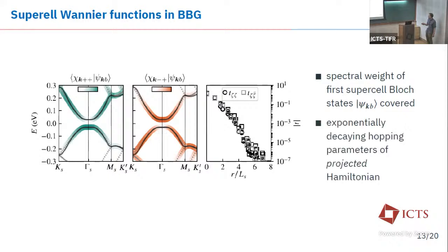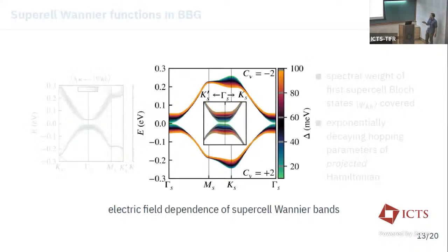As a control, we have plotted the hopping parameters when projecting the Hamiltonian onto those Wannier states, and we see that they decay strongly exponentially, meaning that we have a well-localized Wannier basis for our problem for the Bernal bilayer graphene in the supercell. And what we can do now is we can take those Wannier functions at certain values of the vertical displacement field, which is shown here, and we interpolate the hoppings in between those gray points, and we see that we perfectly interpolate also the band structure that we get out as a result.